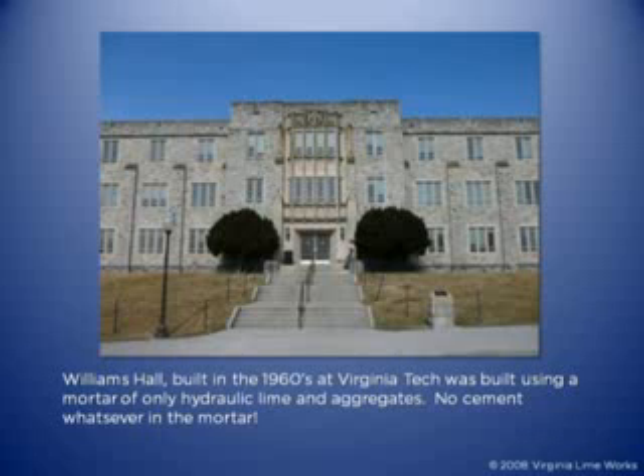I'm used to seeing Portland cement-based mortars when we're looking at buildings from the 1960s. We happened to stumble across the original specification for the project, and the mortar mix was a hydraulic lime sand mix. And they realized that a hydraulic lime mortar would perform far superiorly to a cement-based mortar with this type of stone that they were building with. And actually today, with some of the buildings that they're building on campus now, they are having problems with their mortar because they're using a Portland cement-based mix versus a lime-based mix.